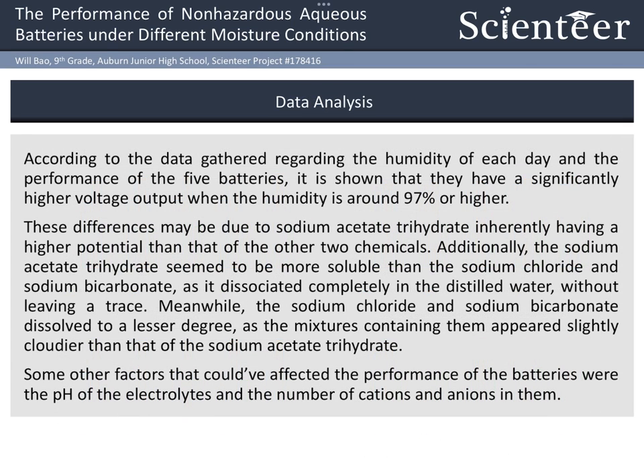By analyzing this data, I found that the sodium acetate trihydrate batteries have a significantly higher voltage output than the other batteries, especially when the humidity is around 97% or higher, and this difference may be due to sodium acetate trihydrate inherently having a higher potential and solubility than the other chemicals, and it may also be due to factors such as the pH of the water after the electrolytes dissolved in them, and the number of cations and anions in them.